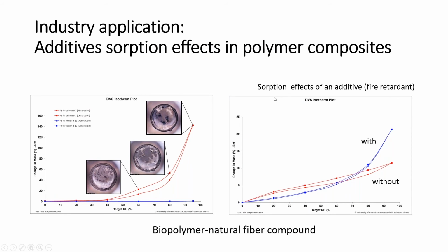Another example, and if Günther Wuzeller is among the attendees, he knows these graphs because there was a collaboration with him. This is an interesting small study within a project that he was running. I won't tell any big details on it, but it was a polymer composite material where a mixture of a biopolymer and standard polymers with a natural fiber network was included. So it would be a biopolymer natural fiber compound. And because it was necessary to equip that material also with a fire retardant agent, the fibers were treated with a fire retardant agent component.